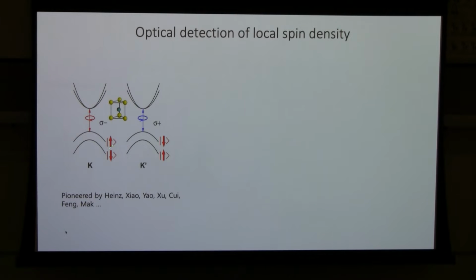The idea, as Tony and many others have shown previously, is that in transition metal dichalcogenides the band minima sit at two different momenta in the Brillouin zone, known as the K and K prime valleys. These two valleys have very different optical selection rules. If you use left circular polarized light, you can only excite excitons in the K valley. When you use right-hand circular polarized light, you can excite excitons only in the K prime valley. At the same time, this system has very strong spin-orbit interaction, and that leads to a phenomenon known as spin valley locking. What it means is that if you add a hole into the K prime valley, it's always spin down. And if you add a spin up hole in the system, it will have to go to the K valley.